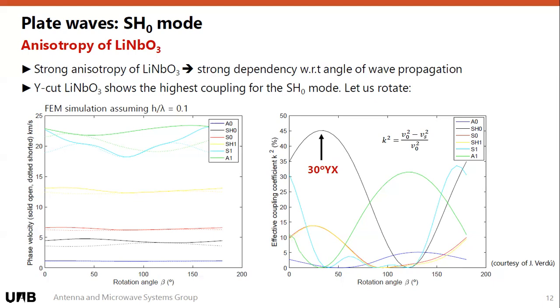So it says you have nothing in there electrically, and then a short circuit condition, you have two infinitesimal thin metal layers there. You can simulate both the open and the shorted velocities, and from those you can actually compute the achievable coupling. What we see here on the black line is the achievable coupling for the SH0 mode, for an orientation having a really big maximum at 30 degrees rotation from the y-axis.